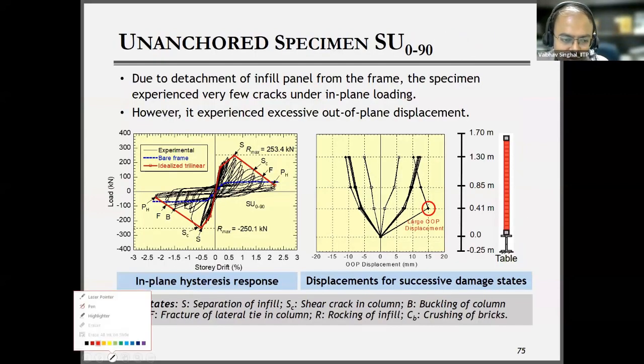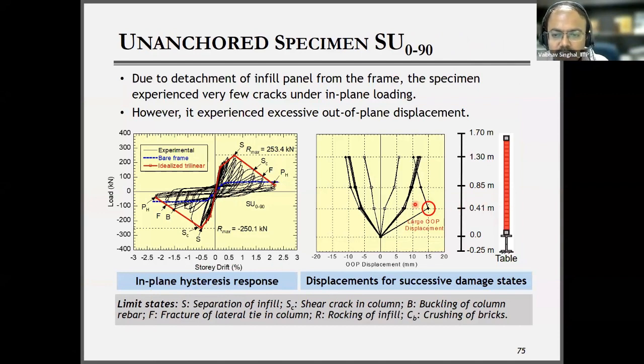So again, for this wall, when the fabric was not anchored, there was large out-of-plane displacement again, to the amplitude of 15 mm, especially at the bottom part, because the bottom part was completely debonded. The separation was also seen quite early. You can see the separation by the letter S. The separation was again at about 0.5, 0.75% drift.